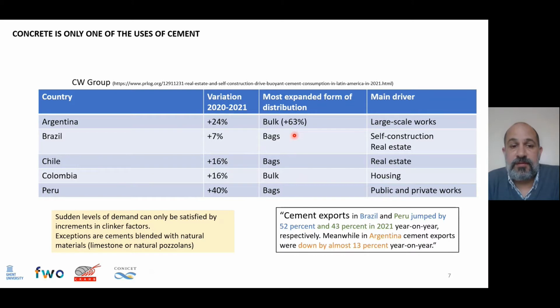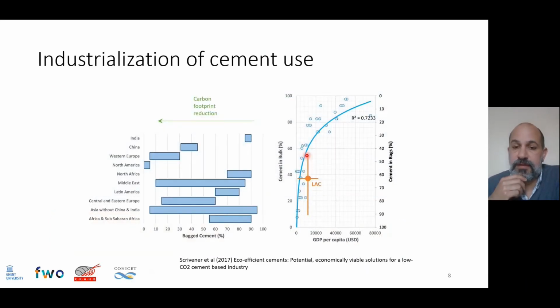Sudden increments in the level of the demand, such as the ones I'm showing here, are hardly satisfied by some supplementary cementitious materials. So when we have an increase in demand, we can easily produce more clinker, we can easily mill more limestone or natural pozzolans, but normally for blended cements that contain slag or fly ash, it's more difficult to find the sources of these SCMs so we can maintain the clinker factors at the same level. So peaks in the demand normally result also in peaks in the value of the clinker factor.